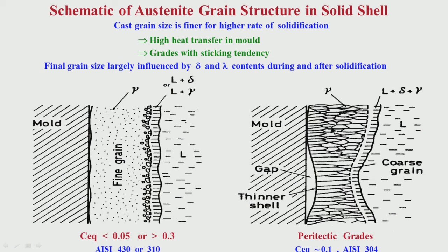So, as I have told you, depending on the type of solidification characteristic, we must use different mold powder having different characteristics. Here we have to take care of the friction. Friction is relatively high, we should not allow too much friction, otherwise there will be a sticker breakout. Here it is just the reverse, there is no sticking, there is air gap formation. So, heat transfer is getting affected, that means too much depression. So, we have to control the depression, we have to see that the uniformity of heat transfer is there throughout the periphery of the mold, that is what is important here.